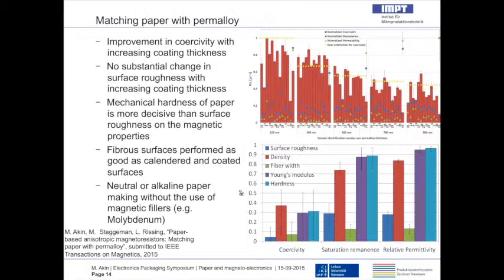What we have seen, increasing the coating from 100 nanometers to almost 1 micron, is that there is really no substantial change in the roughness of the surface. We are talking here of average roughnesses of up to 3 microns, whereas 1 micron of coating wouldn't level up that roughness. Still, with increasing coating, we obtained a decrease in coercivity, those red bars in this graph. This is actually given by theory on smooth surfaces, and it is happening on the paper substrates, where the yellow dots are the theoretical model of how the coercivity of the coating on a smooth surface should decrease with increasing coating thickness. This is what we almost obtain, or similarly obtain, with the coatings on paper.